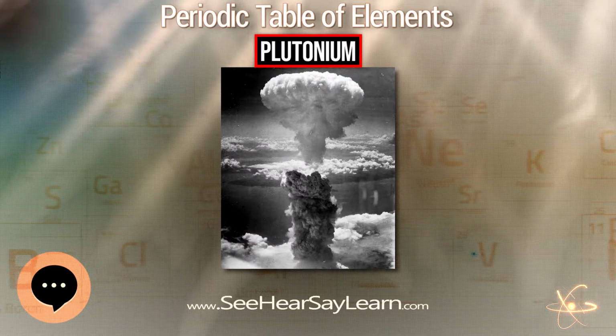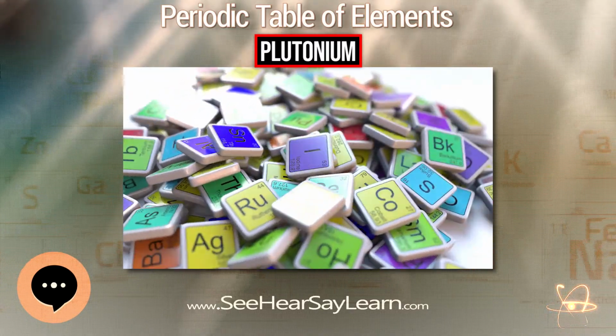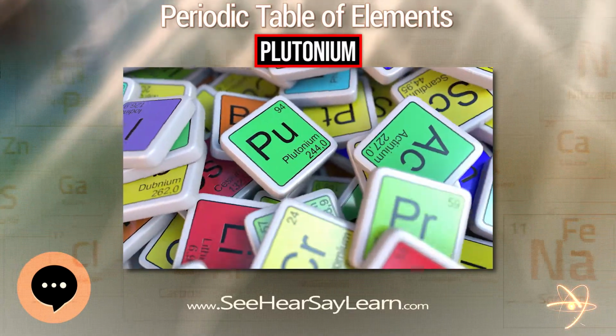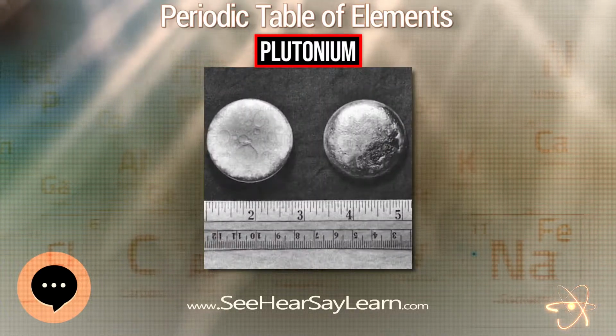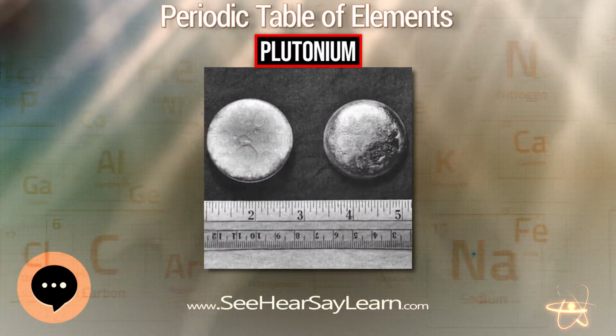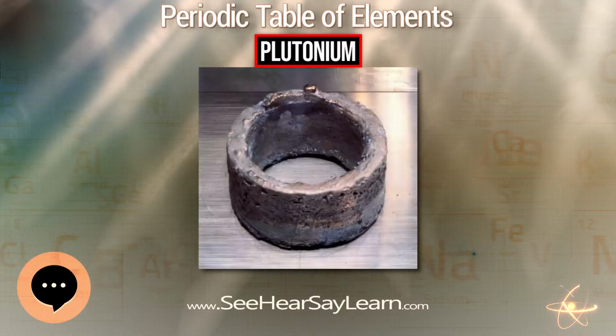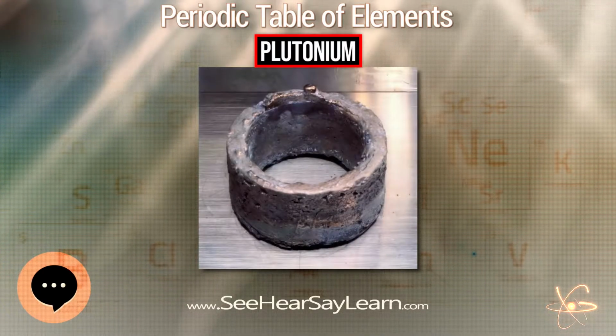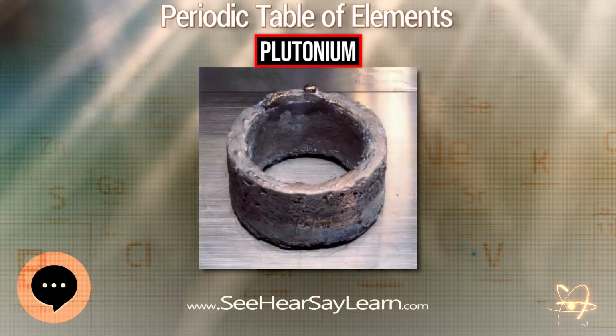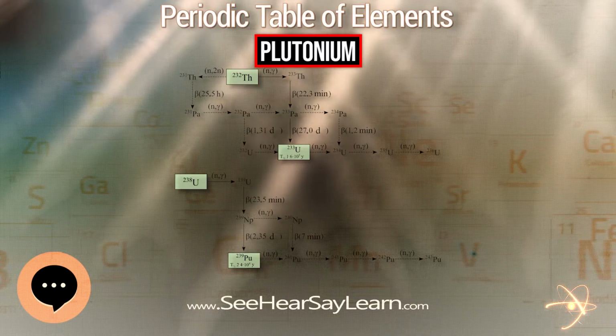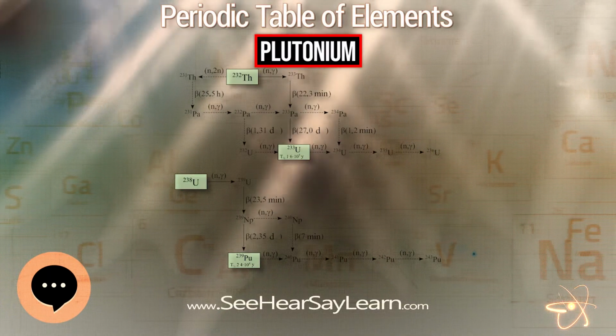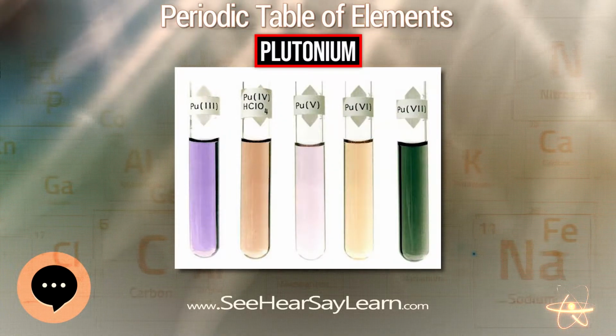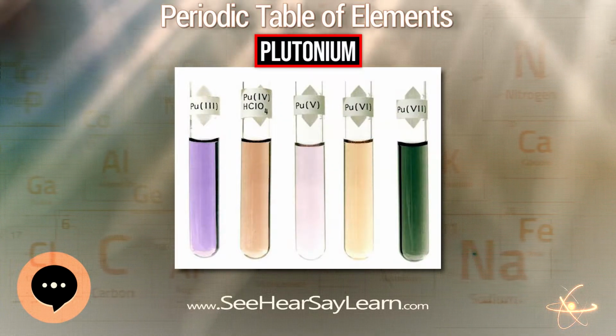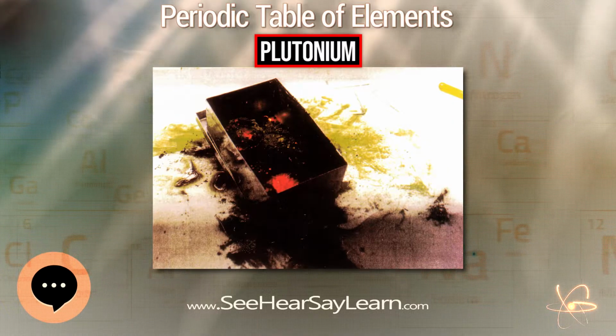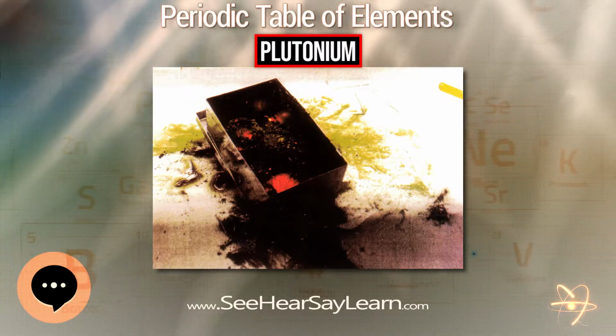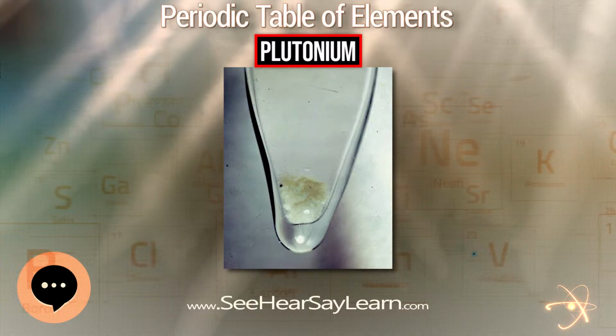Powders of plutonium, its hydrides, and certain oxides like Pu2O3 are pyrophoric, meaning they can ignite spontaneously at ambient temperature and are therefore handled in an inert, dry atmosphere of nitrogen or argon. Bulk plutonium ignites only when heated above 400 degrees C. Pu2O3 spontaneously heats up and transforms into PuO2, which is stable in dry air, but reacts with water vapor when heated. Crucibles used to contain plutonium need to be able to withstand its strongly reducing properties.